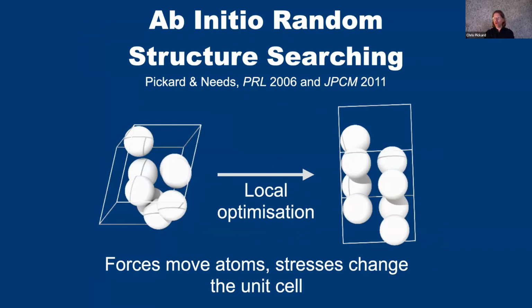So that's the mission we set ourselves, and the method I developed for that is so simple. I hope that all of you on the call would think of it as a way to predict crystal structures, although you may not be sure if it was going to work or not. The approach we took was to fill crystalline unit cells with atoms randomly. Initially the code was a simple bash script that pasted in random fractional coordinates for carbon atoms into a unit cell, and then fed that randomly generated input unit cell into a code like CASTEP to do quantum mechanical structural optimization. Now, if you do it just once, the odds are you probably won't find the ground state structure. You'll probably get stuck in some highly energetic or even just slightly energetic metastable phase.